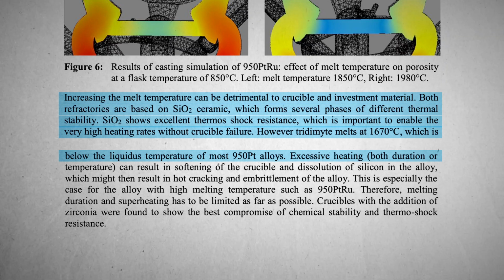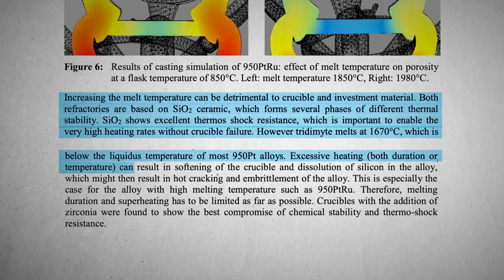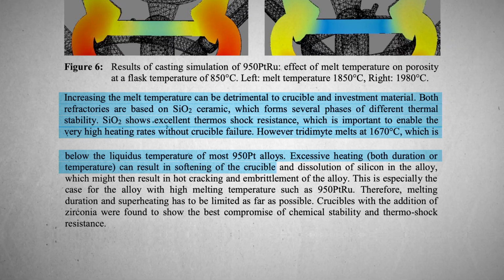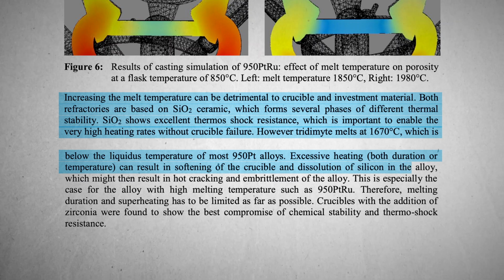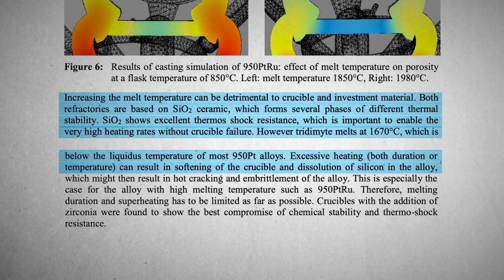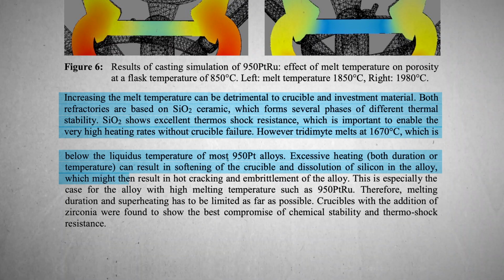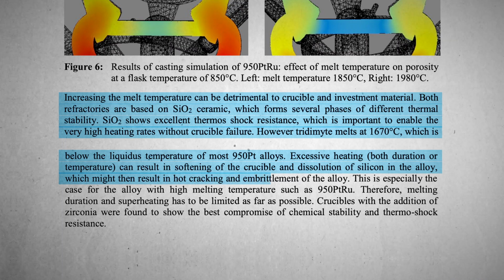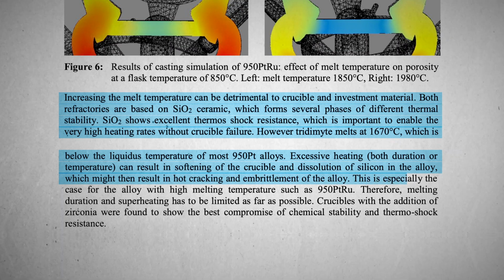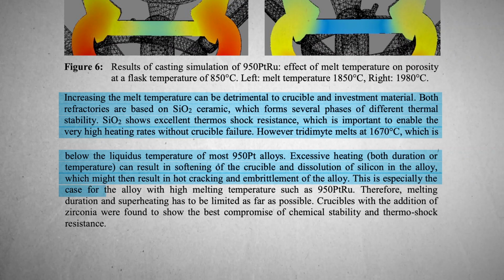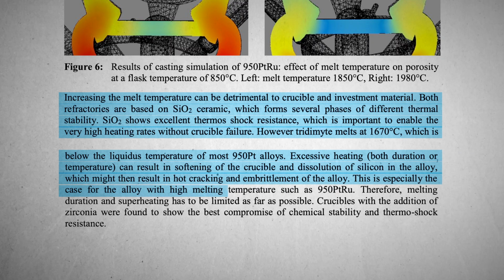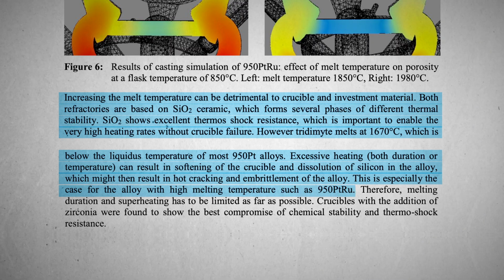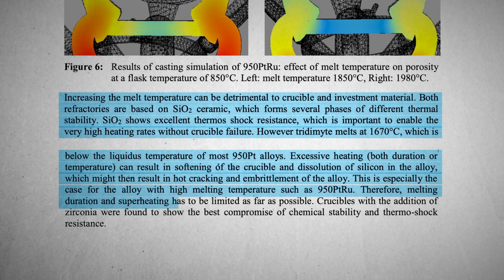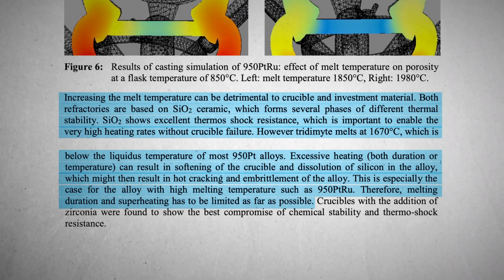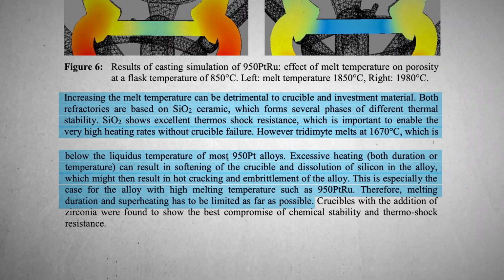Excessive heating, both duration or temperature, can result in the softening of the crucible and dissolution of silicon in the alloy, which might then result in hot cracking and embrittlement of the alloy. And this is especially the case for the alloy with high melting temperature, such as 950 platinum ruthenium. And therefore, melting duration and superheating has to be limited as far as possible."